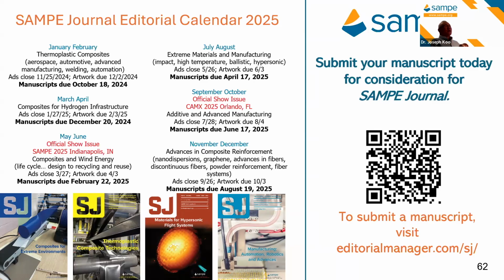Yes, nano materials, you do not need to put much. The rule of thumb, I always say 5%. You shouldn't be putting so much nanomaterials, and it's not a nanocomposite anymore because you need to examine the dispersion. Can you put 10 weight percent CNT in there? You're wasting your money. You shouldn't be using 10 weight percent of CNT in your resin system. You need to see how well it's dispersed, and that is very important. Okay, thank you.